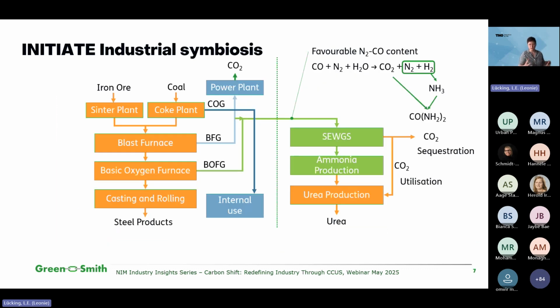Just to give an insight into how this Initiate project works. By creating a symbiosis, we are able to use the off gases that have a favorable nitrogen and CO content to our advantage to produce ammonia and then urea. This is because our technology converts CO with steam to CO2 and hydrogen. It then separates the CO2, so we have a nitrogen-hydrogen mixture, which we can then convert into ammonia. And lastly, in a further step, we can convert it to urea, for example for the agricultural industry. This process does still require sequestration because the urea process doesn't need as much CO2 as the traditional steel mill produces. But some of the CO2 is actually utilized in the urea.